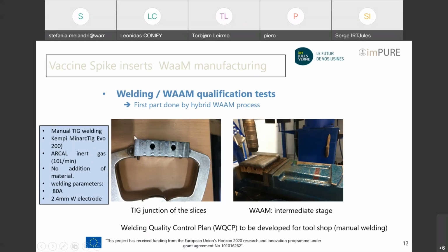Also, to reduce the warping and the distortion, as we have 7 slices, we have 6 joints. We alternate top-down welding, and that's why at the end the assembly was very flat with very low distortion.